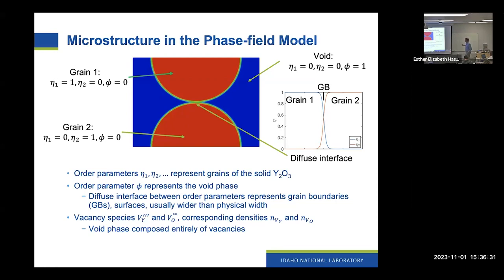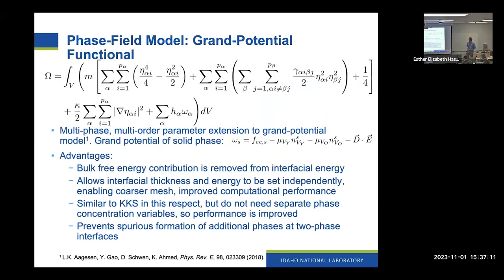If this wasn't clear before, hopefully this makes the meaning of the diffuse interface more clear. In grain one, order parameter one has a value of one, and in grain two, order parameter two has a value of one, and then we have this diffuse variation of the two through that interface. In this model, we don't have fission gas, but we do track vacancies. We track vacancies on both the cation and the anion lattices, and we assume a net charge for those vacancies, which we want to account for due to the interaction with the electric field. So the void phase is composed entirely of those vacancies.